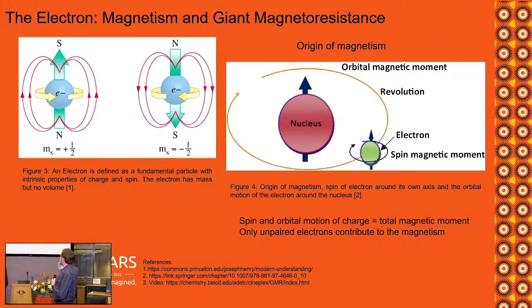The other thing is the electrons are spinning, so the charge is spinning, but the charge does not exist alone. In iron or in chrome, this charge is rotating around the nucleus. It's moving, so you've got two motions. First, you've got the charge moving, the electron, with its own field, its own magnetism. And you have this electron moving around the nucleus, which produces what's called orbital motion. And in things like iron, chrome, nickel, cobalt, this interaction is actually very complex. But most of the magnetism actually arises, in effect, because of the electrons. They're the ones that, in majority, give you the magnetism.